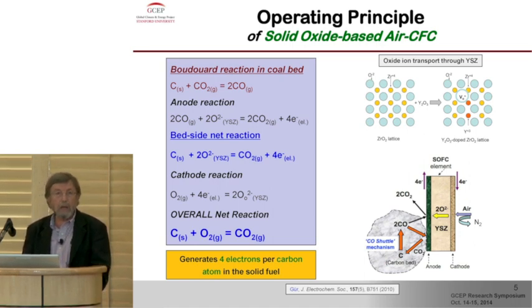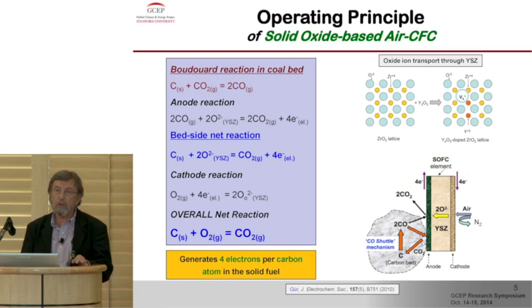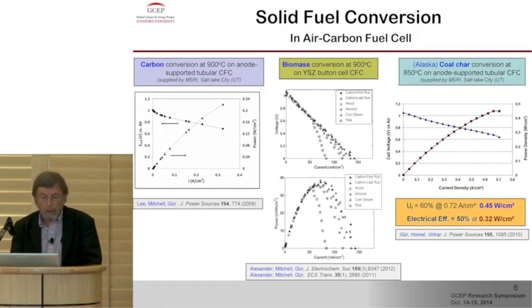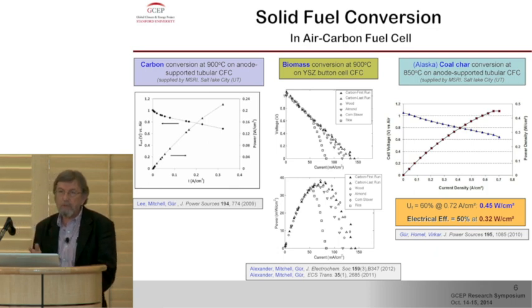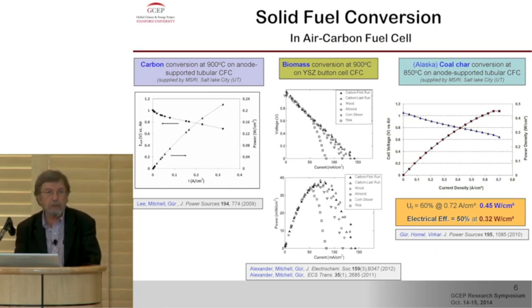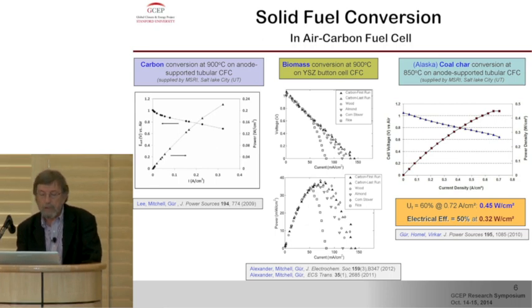At the end of the day, what we have, again, is carbon plus oxygen going to CO2. We generate 4 electrons through the external circuit for every carbon atom that is consumed in the coal bed or in the carbon bed. And we demonstrated this concept, it's a fundamentally sound concept, with many different solid fuels. This is for carbon. We got close to 220 or 230 milliwatts per square centimeter.